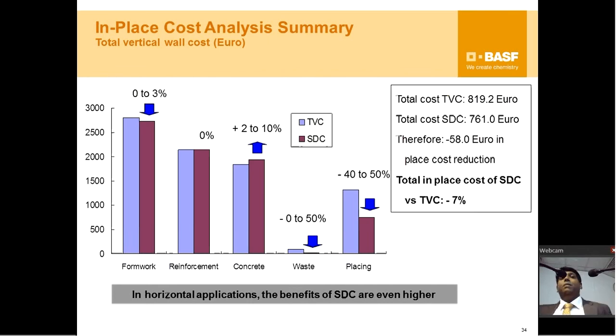And I remember the caution here is all in a batching plant. For any concrete, you need to be very careful about the moisture content in the sand, the water absorption of your sand and aggregates, all these things. That's the regular quality control. And for this, the same also has to be maintained in the same way. But the caution is that if it is not done properly, and remember this is a highly flowable concrete, and the moisture content is not corrected properly, you could get segregation. Okay, but that quality control, even for regular concrete you will anyway have problems. The same holds good for this as well.